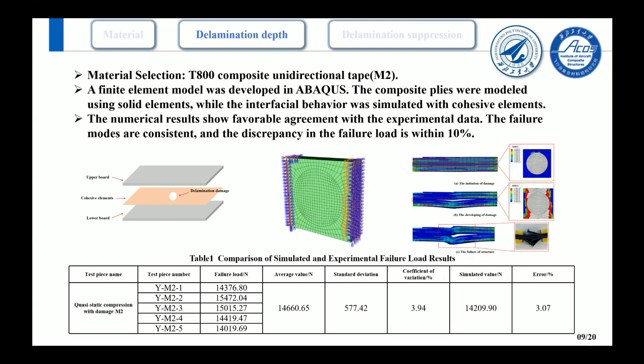The second part of our research primarily utilized finite element simulation to investigate the influence of delamination depth on the residual compressive strength of composite laminates. A single composite laminate material was selected, and a finite element model of a laminate containing a single delamination was developed in Abaqus. The composite plies were modeled using solid elements, while the interfacial behavior was simulated with cohesive elements. A comparison between the simulation results and the experimental data showed consistent failure modes. Furthermore, the error in predicting the failure load was within 10%.